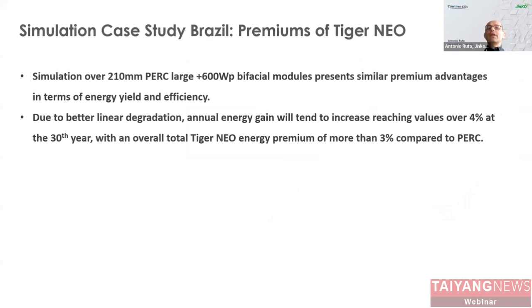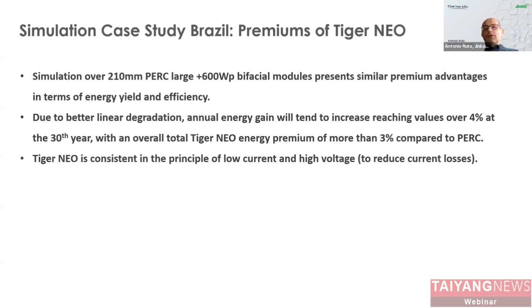We need to consider, do not forget, the linear degradation, the concept that has been emphasized before by my colleague. If we consider the gap in production, because we have less degradation, the energy yield gap will increase year by year. So practically we will have, at the end of the day, 4% more in terms of production, because our modules degrade less. Overall, total energy will be 3% more. And all Tiger Neo is consistent with the principle of low current. This is because of the size of the cell. So this avoids a lot of headaches for the designer, especially when they design the safety part of the design of the PV system.